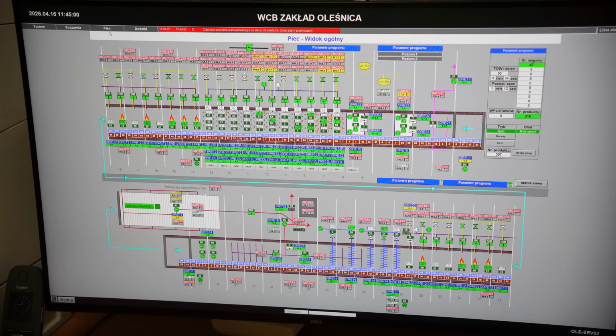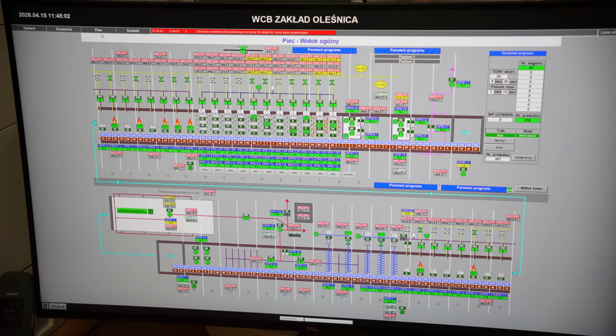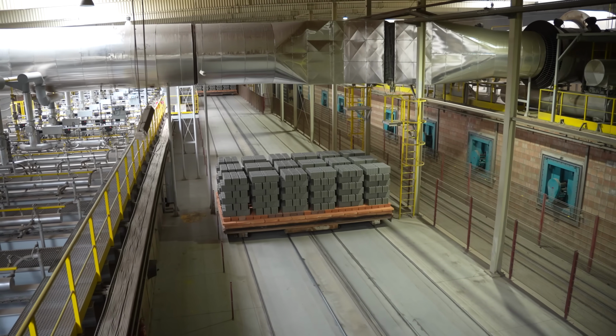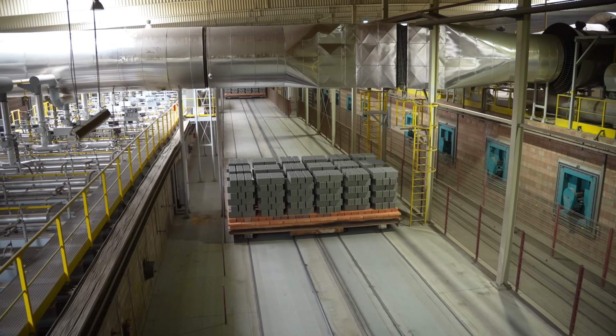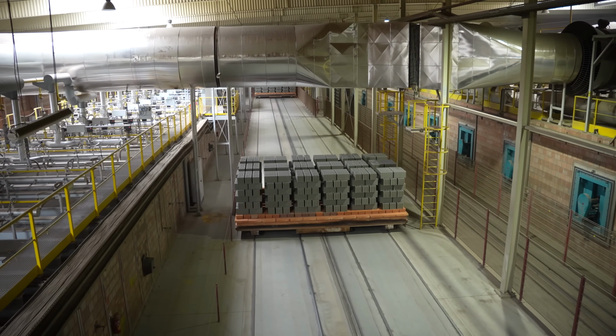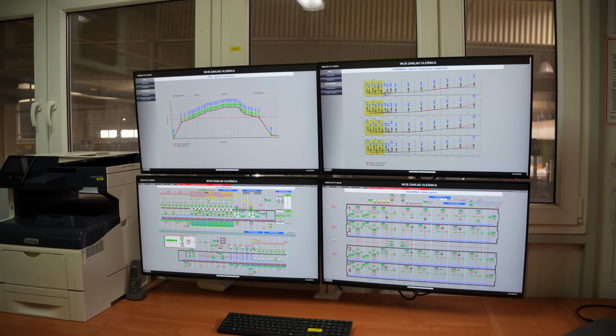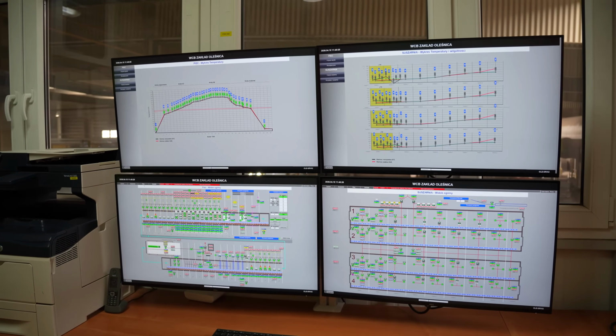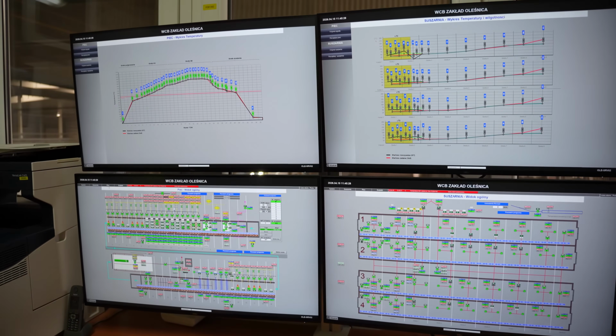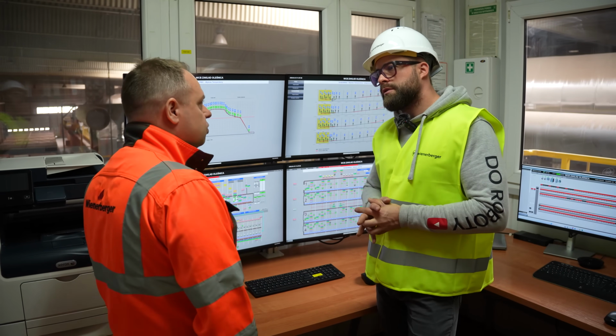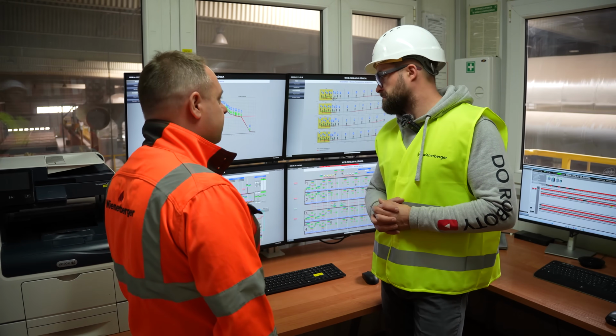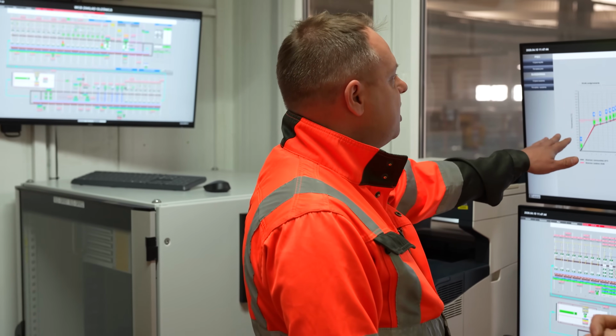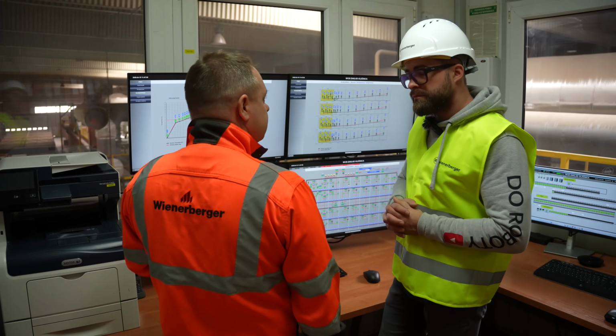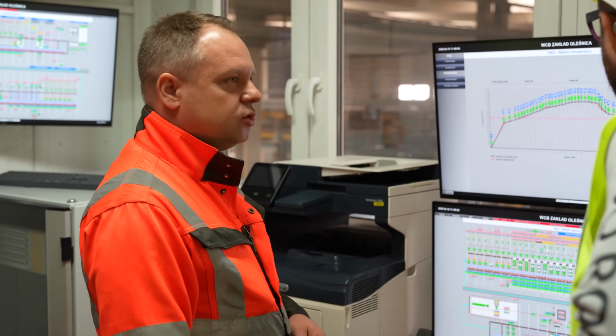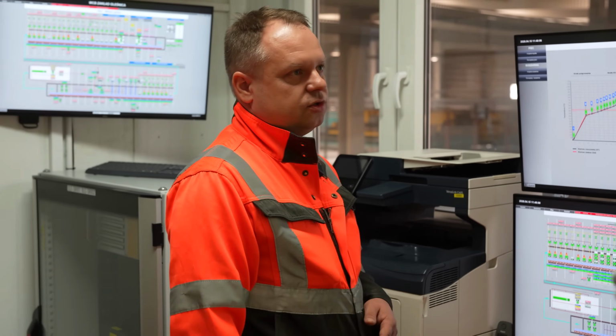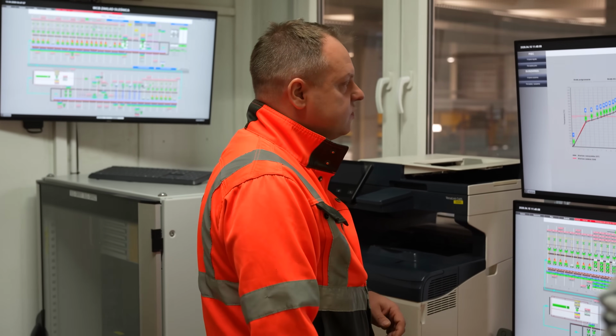Here on the diagram, we can see a visualization of our kiln, and the carts are entering the airlock. Where then, with each movement, do they move deeper into the kiln? In the kiln, we have 15 HG burner sections and 16 SB burner sections, which let us properly control the temperature and firing process. For each brick size, we have a specific firing program prepared. Here we can see the course, the actual progress of the firing process, and we check if everything is proceeding correctly. The entire technological process takes about 17 to 19 hours, depending on the format.